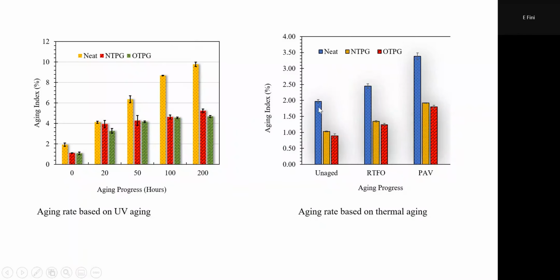You can see how the aging index goes up with the blue, which is neat asphalt. And we always expect that. We always do aging. We know that it's getting worse, but we just don't want it to get worse that fast. We don't want it to get worse that much. We want to delay it. So in this case, when we added the plastic, the bars are always shorter, and the rate of increase, when you go from unaged to RTFO to PAV, if you look at how fast they increase, that's much lower than the slope or the rate that you see for the neat. So maybe plastic is delaying the aging in this case.